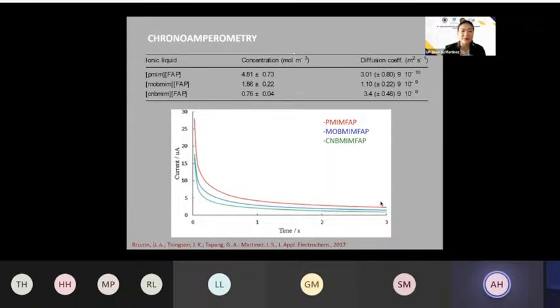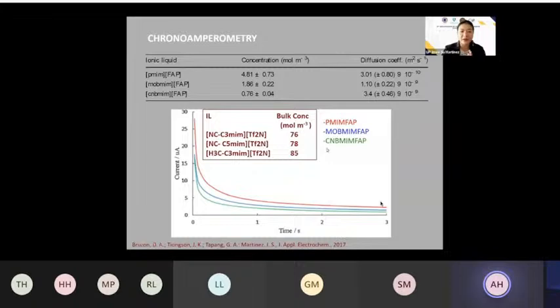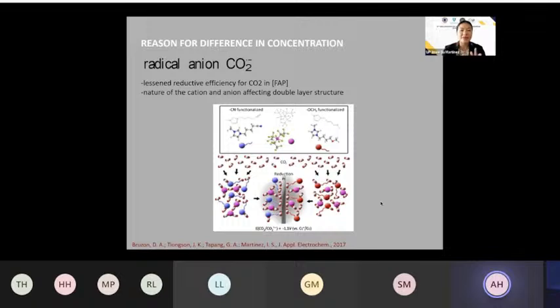As you can see, these are the concentrations of the carbon dioxide dissolved in our ionic liquids. And then these are the diffusion coefficients, which are really quite high and are actually very good. However, if you compare the concentration using chronoamperometry with the bulk concentration, you can see the very low amounts in our chronoamperometry measurements. This is probably because of the technique itself, wherein we actually only measure the amounts of carbon dioxide that are reduced on the electrode in our setup, as opposed to the actual measurement of the carbon dioxide dissolved into the bulk of the ionic liquid using the pressure drop method. And this is the reason why it's good to always do two complementary techniques when performing an experiment.